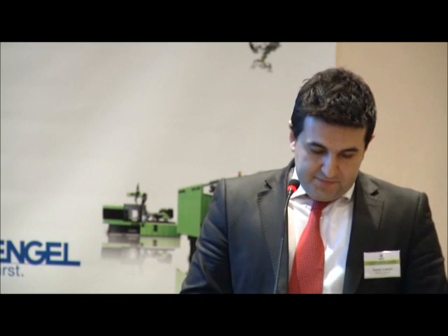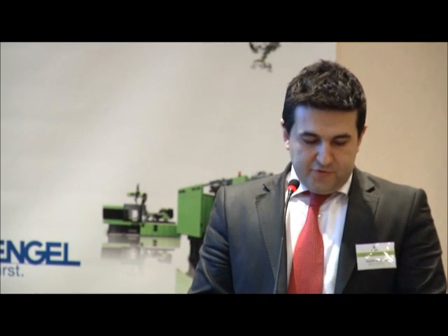And the material expansion technology. A roll of solid plastic is prepared for saturation by layering it with a porous material. The roll is then pressurized with a gas such as food-grade carbon dioxide. The interleaved porous material provides a pathway for the gas to saturate the polymer roll. Once saturated, the polymer is removed from the vessel and heated. As the polymer softens, billions of gas bubbles nucleate in the polymer, reducing the density and causing an expansion. In general, this process increases the length and the width by 150% and the thickness by about 200%. This expansion results in a dramatic decrease in density, typically about 20% density relative to the original polymer.